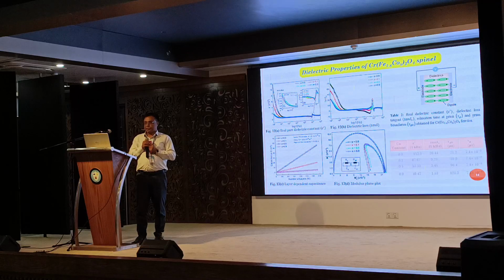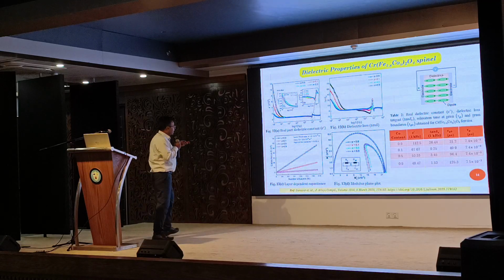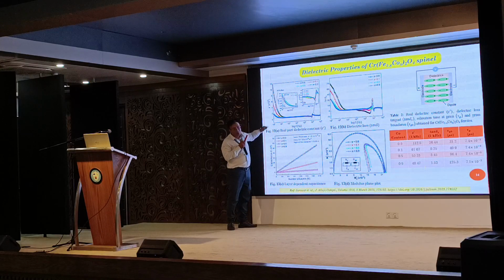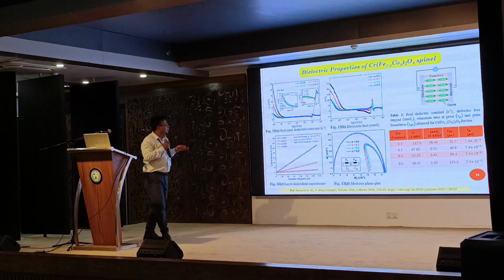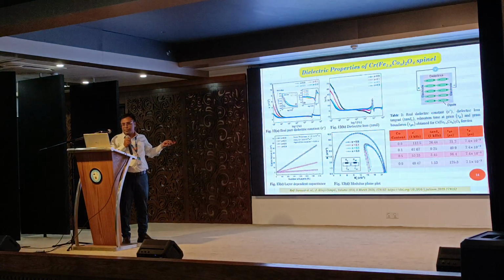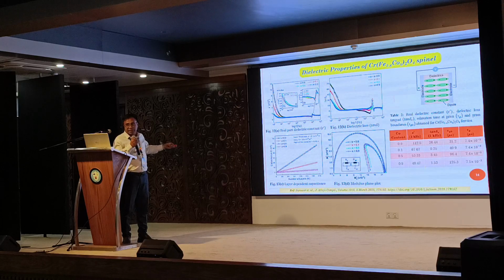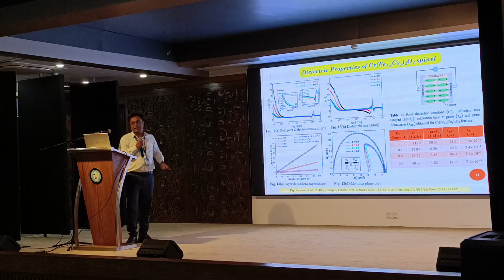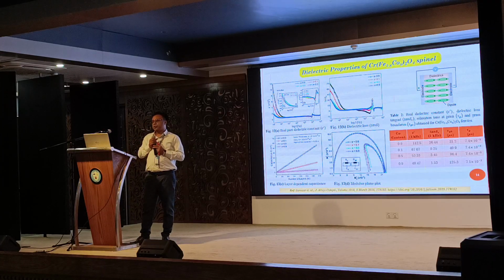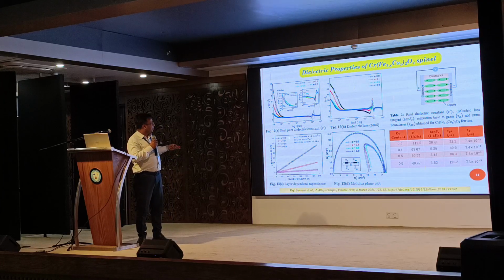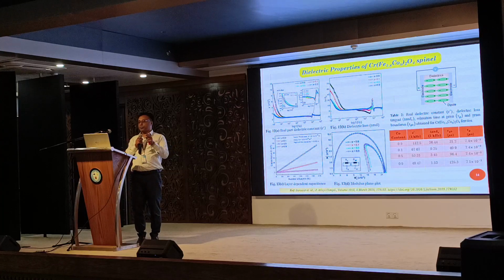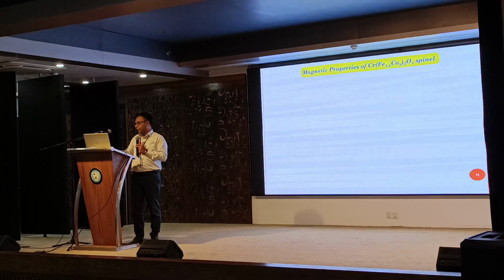Then we measured this, and we found that our dielectric constant is actually decreasing. The black one is our undoped sample, and whenever we implemented our doping there, a cobalt atom, the dielectric constant continuously decreases, and finally we found that this material is actually not good for storing energy. It will not store energy, because at first I told you my target is to make a sample for communication, so I confirmed that there, but the dielectric loss is also decreasing here. Dielectric loss is also very low. So it is perfect for application, but not for energy storage, for communication. How did I confirm that?